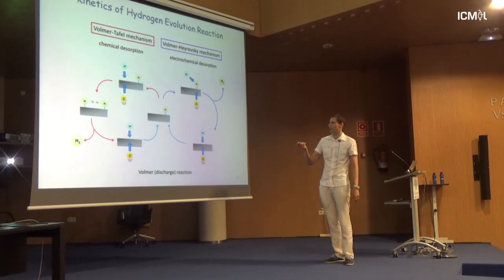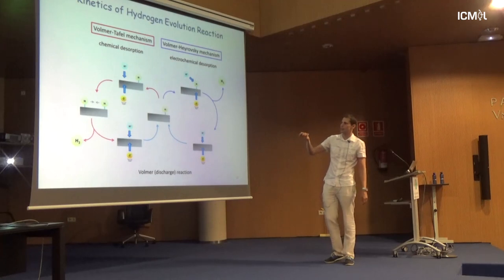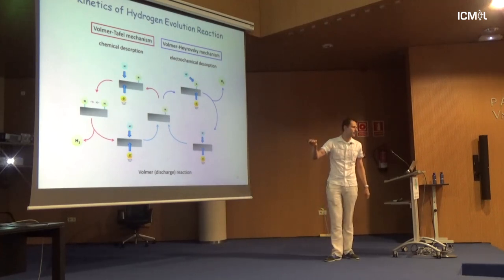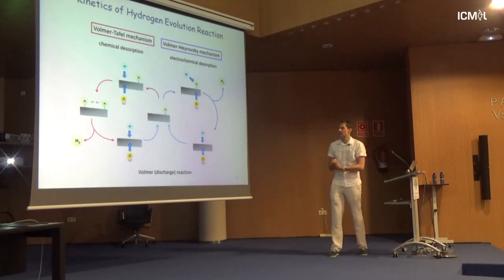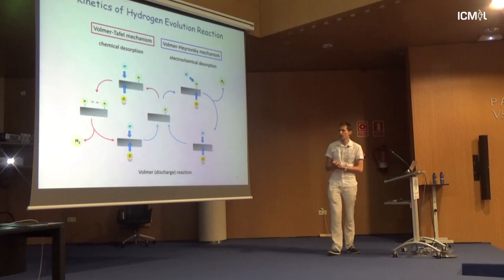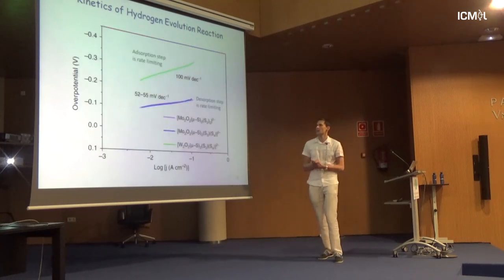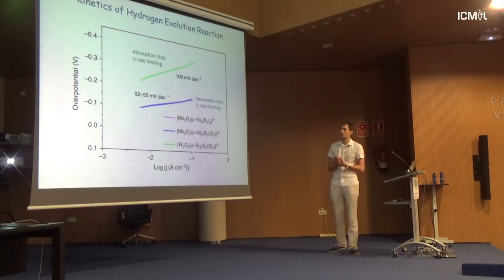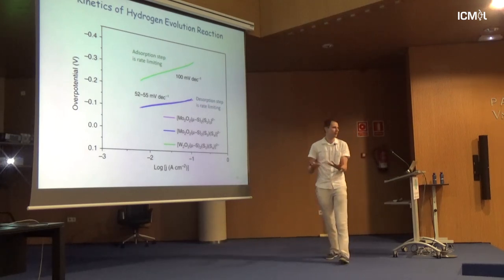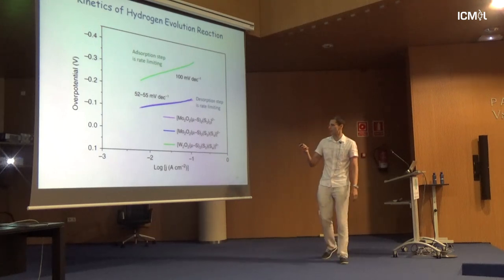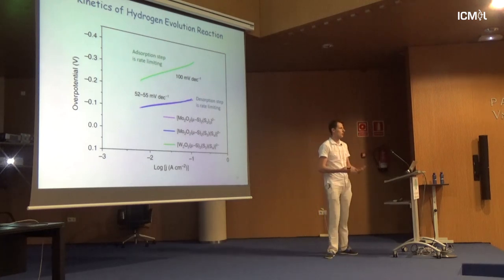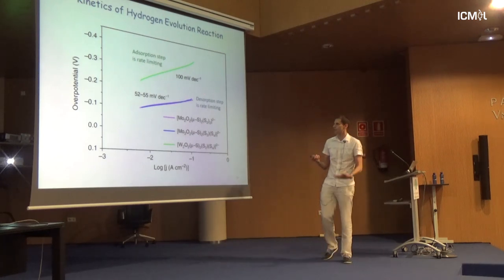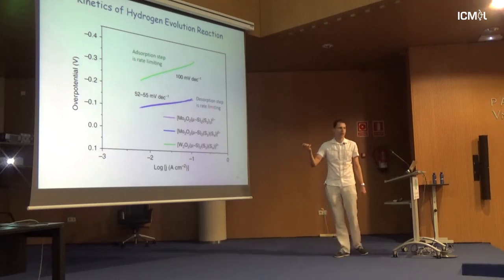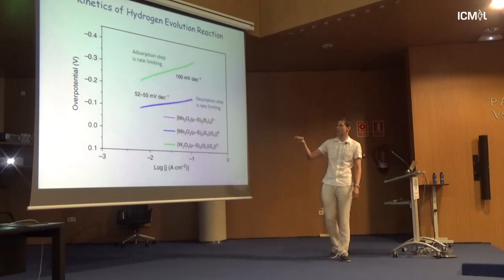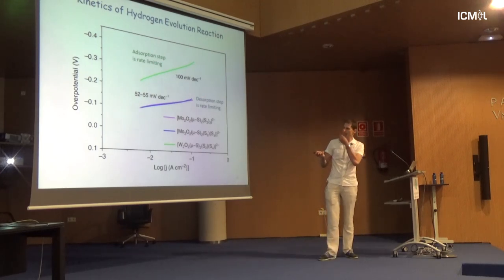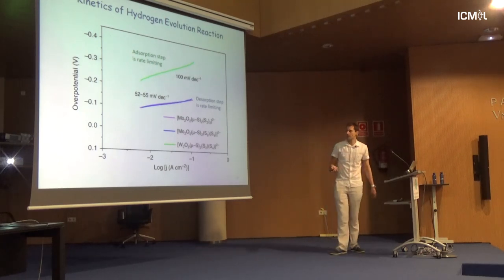Alternatively, you have hydrogen adsorption, and then another hydrogen gets adsorbed, and they migrate and recombine at the surface. This is a different mechanism. What's brilliant about this electrochemistry is that by plotting your overpotential versus the logarithm of current density, you get curves which indicate the rate limiting stage. And what we see is that these are absolutely identical, just spot on, with exactly the same kinetics of reaction, but the tungsten is very, very different.